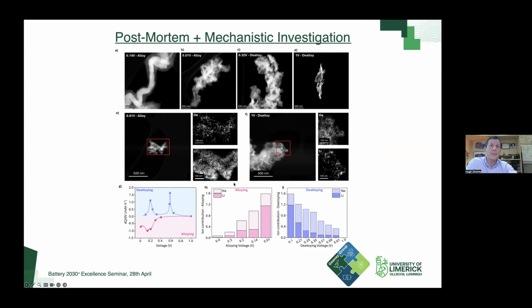Through clever experiment design, this is the differential capacity plot of the profile shown again. What Saeed did was take electrodes at various points along this profile and perform ex situ ICP analysis. That allowed him to decouple the ion contributions during alloying and dealloying.